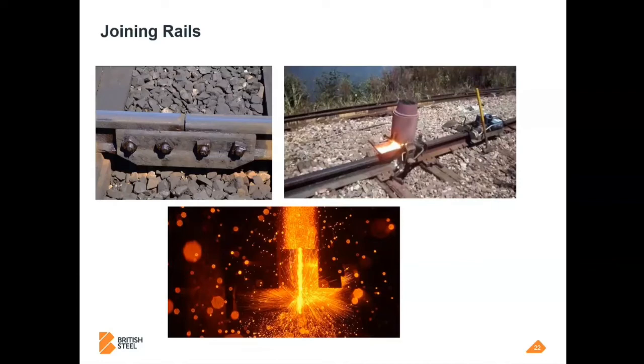You build a mold around a gap between two rails you want to join, maybe an inch gap. You put this crucible on top. You light the blue touch paper and retire 10 paces. A lot of sparks fly, and it casts iron out with some alloying within the powder. It's a bit more than just cast iron. It's quite clever, really, the technology behind it nowadays.